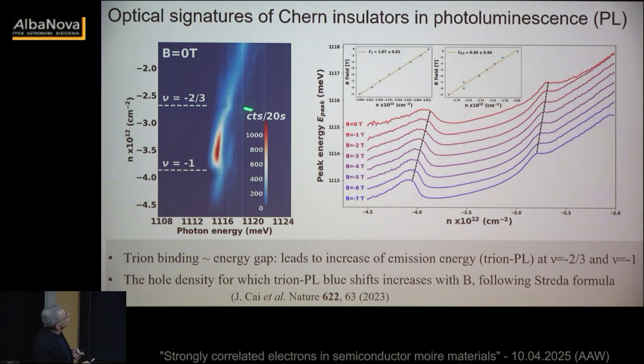All right, so now why do I say that these are topological Chern bands? So this is an experiment of photoluminescence, which I haven't shown before, which was first done by Xiaodong Xu 2 years ago. So this is photoluminescence as a function of doping. At 2/3, there is a cusp, and at nu equals 1, there is a cusp. I told you that these are associated with incompressible states. What is important, though, is that if it's a trivial incompressible state, if you apply a magnetic field, this will remain exactly at this density. Not so for topological states. The topological states follow the Streda formula, which tells you that as you increase the magnetic field, there should be a shift increase in the density that is needed to reach that particular Chern insulator state.